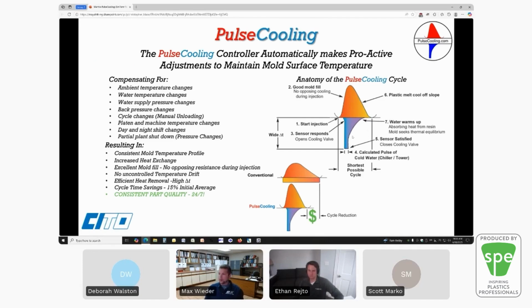Once the pulse cooling cycle is optimized, then no matter what the temperature or season or any other variable you'll have in your cycle, it will make those proactive adjustments to maintain that mold surface temperature profile to mold a consistent part 24/7. As you can see, the cycle time reduction comes from that wide delta T. That's where we're pulling all the energy out of our mold with that calculated pulse of cold water. The cycle time reduction from efficiently removing the heat by sending that cold water to where it needs to go offers us the largest potential for profit in our cycle.